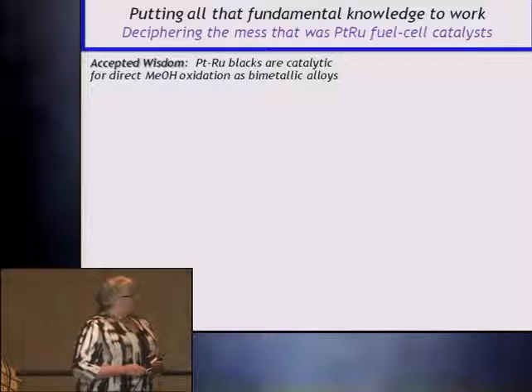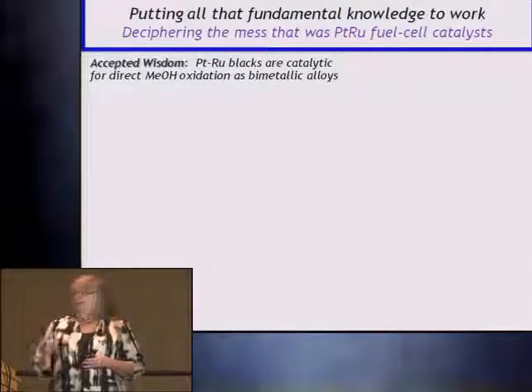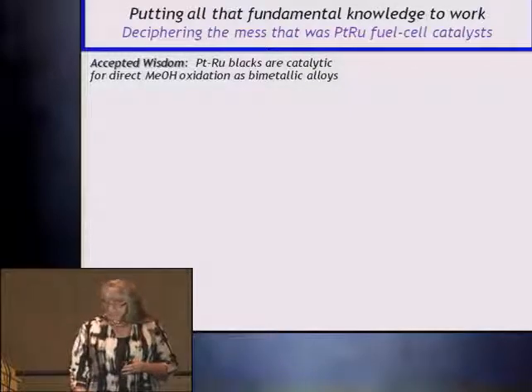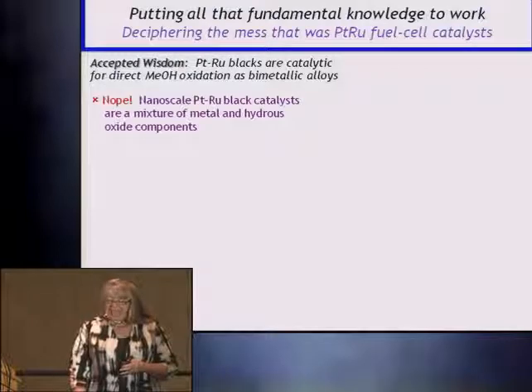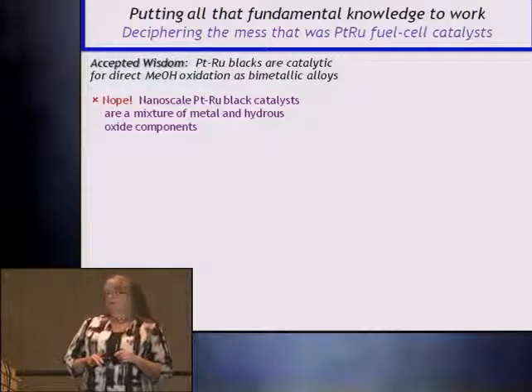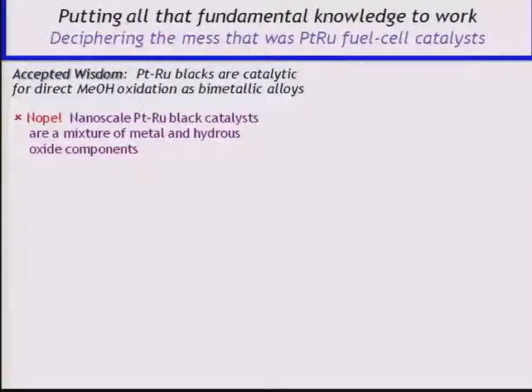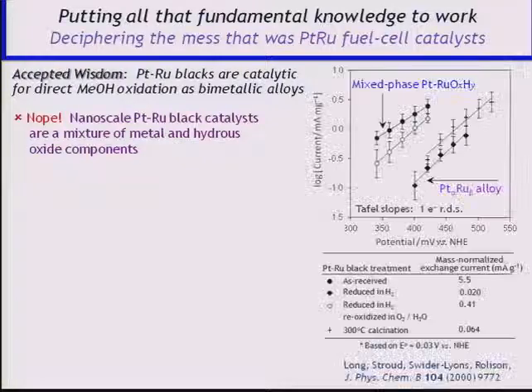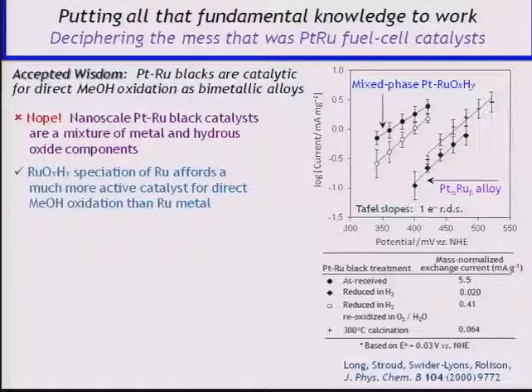Now, the folklore, the wisdom was that these blacks, although nanoscopic, were alloys. All that work had been worked with bulk alloys, and people understood the methanol oxidation mechanism fairly well. But once we started analyzing these real materials, we found that there was barely any alloy there. It was platinum with a lot of oxidized forms of ruthenium. And so if you electroanalyze that, do a Tafel plot, the equilibrium value for the methanol is about here. Here's where the Tafel slope for the alloy is going to come out. So this has been reduced in hydrogen to make it like an alloy. What came out of the bottle, which was an absolute mess, gives you the highest activity. It's 250 times more active than the nanoscale alloy. And the ruthenium hydroxylated speciation is critical to achieving that activity.